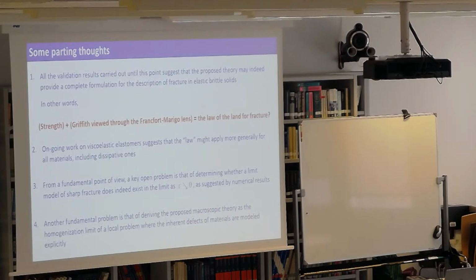Even from a different perspective, coming from a background of homogenization, I'm not entirely satisfied with this theory. This theory is great to apply, but okay, can we actually look at the problem accounting for the defects explicitly and then passing to the limit? Essentially homogenizing the problem, accounting for defects explicitly, and then coming up with a macroscopic theory as the homogenization limit of a local problem. I don't even know how to describe defects geometrically or constitutively, but let's say you do that, and then you pass to the limit, and then a strength should emerge, right, from that homogenization. But again, these are two, I guess, big open problems, but very important for us to understand what really is going on, right?